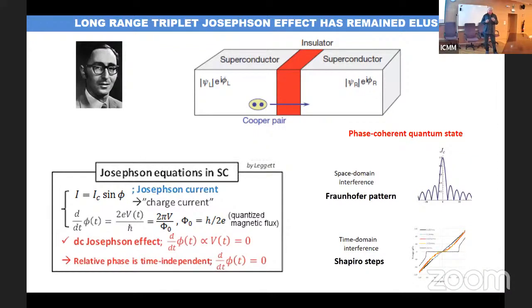So this Josephson coupling gives rise to a phase coherent quantum state. So demonstrating the Josephson effect implies demonstrating phase coherence. And this is shown by very characteristic interference effects, right? The first is the lateral modulation of the critical current, which gives rise to a spatial interference, giving rise to a characteristic dependence of the critical current on magnetic field, which is the Fraunhofer pattern, right? And there is a time evolution of the phase under an applied voltage, which gives rise to synchronization and phase locking under illumination with microwaves. This gives rise to the well-known Shapiro steps. So demonstrating the Josephson effect requires showing Fraunhofer modulation of the critical current and Shapiro steps.